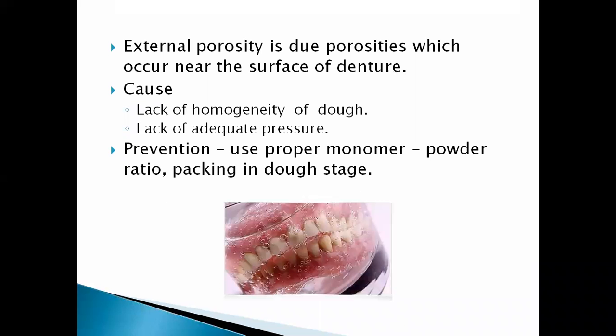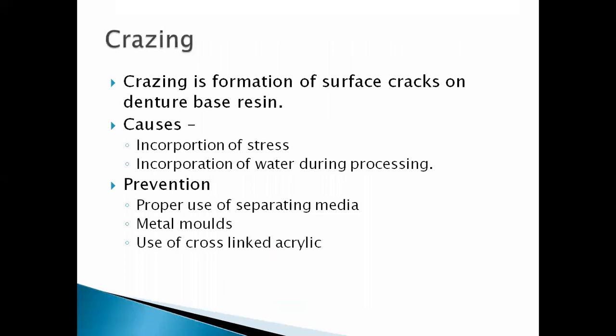External porosities are those which occur near the surface of the denture. They generally occur due to lack of homogeneity in the dough or lack of adequate pressure while clamping the flask. Next is crazing. Crazings are the formation of surface cracks on the denture base. It occurs due to the incorporation of stress or water during processing. It can be prevented by proper use of separating mediums and using metal molds. If you can appreciate in this picture, here you can see small cracks. This is your crazing.